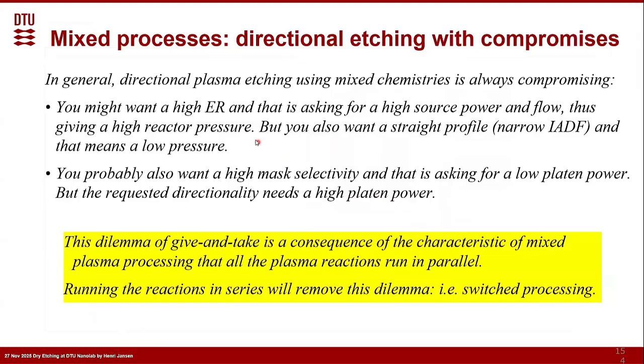The reason is that it works with compromises. You might want a high etch rate, and then you're asking for a high ICP power and flow, thus giving a high reactor pressure. But you also want a straight profile, so you need a narrow ion angle distribution function. And that means a low pressure, as we just saw before with beta, with the anisotropic number. And you also would like to have a high mask selectivity, and that is asking for a low platen power. But again, as we saw for the anisotropic number, we need a high platen power to get this ion angle distribution very strong and very sharp. So this is the consequence that both processes are running in parallel, both the etching and the passivation.